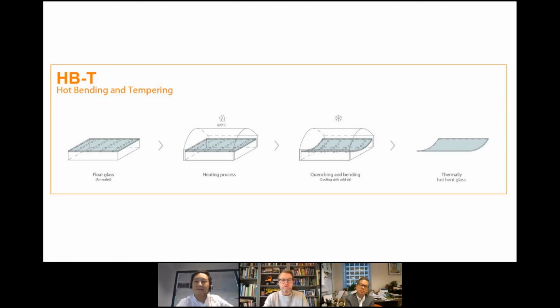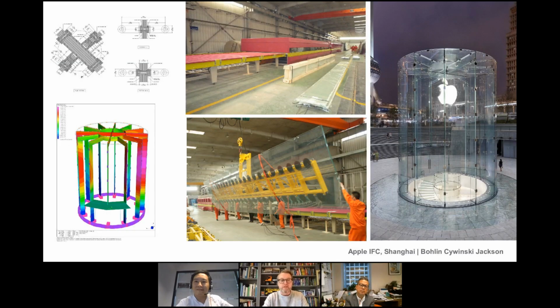And as I've talked about before, this essentially takes flat glass and uses the tempering oven to bend the glass itself into various radiuses. And that's something that, through the work we've done with North Glass, in fact for Apple in China, we developed the process of curving much larger pieces of glass. So here, for example, this project in 2010 was a result of developing a heat curving tempering oven of up to 18 meters. These panels being 12 meters tall, with a radius of about 5 to 6 meters.